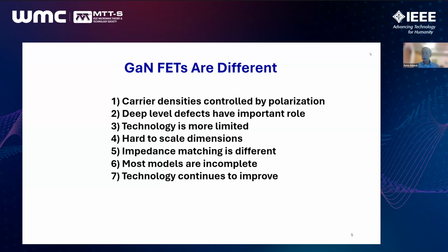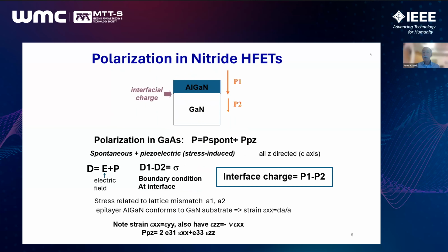I'd like to describe those within this presentation and go through a list of differences one by one. And these differences stem mostly from the materials properties and basic physics, but they do translate into information about how to make the FETs and how to use them. So to begin with, I should mention that as we probably all have heard, the carrier densities within the gallium nitride FETs stem largely from differences in polarization between the channel and the overlying material, typically aluminum gallium nitride.